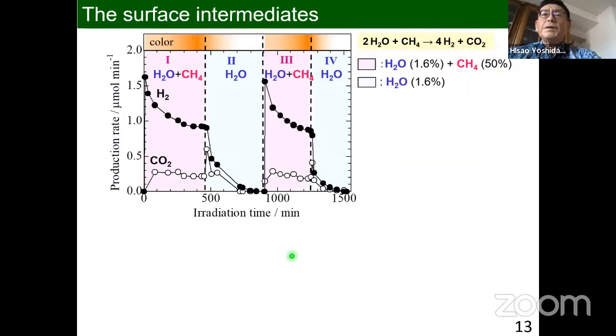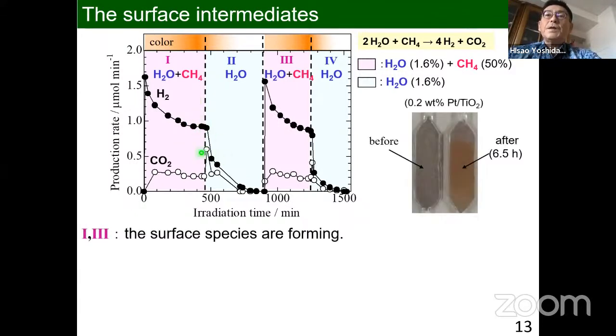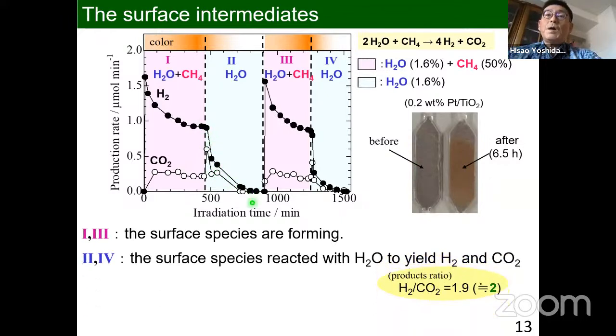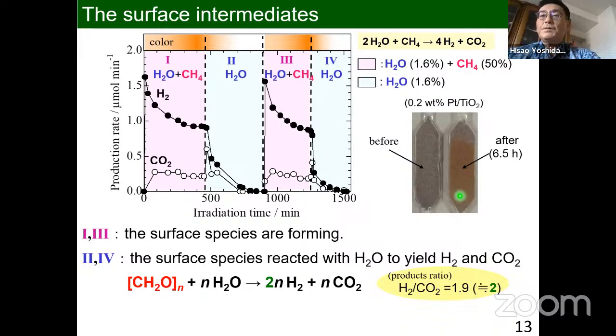Then we operated the reaction conditions. First, the methane and water were flowed into the reactor, and we switched. In this case, we can see the color at the end. And after that, we cut the methane. I mean, only water was introduced. In this case, the color was removed to the initial state. However, in this case, we also observe the products, hydrogen and carbon dioxide, so we think this brown color is an intermediate in this reaction.